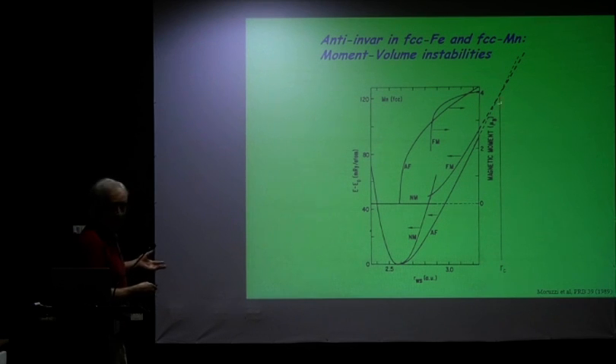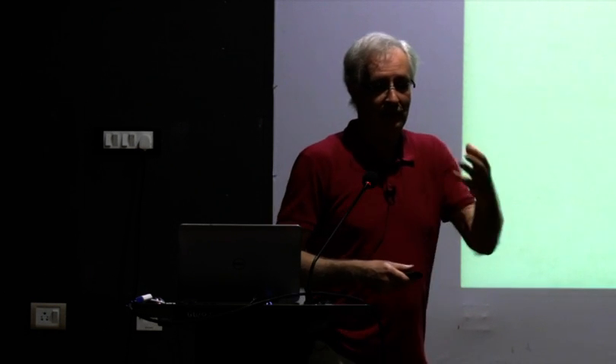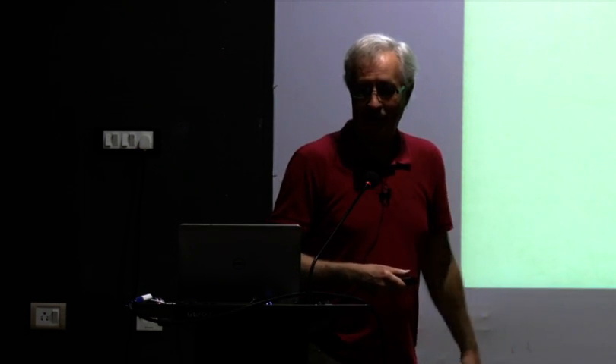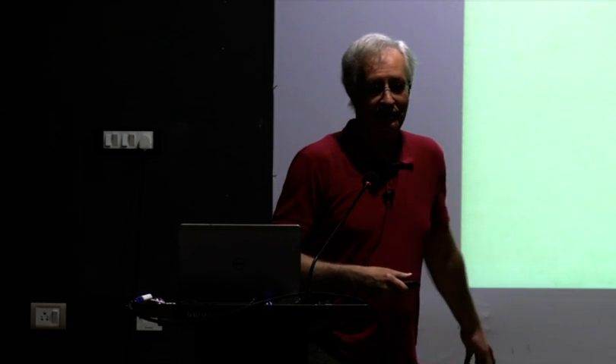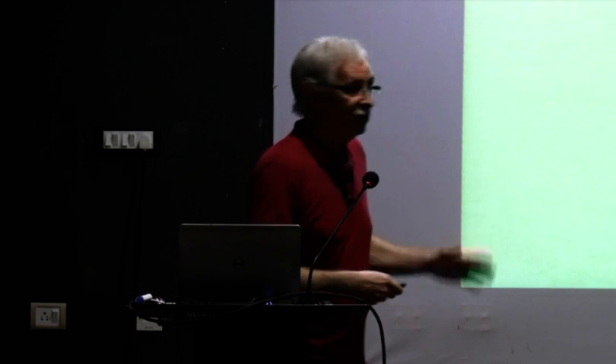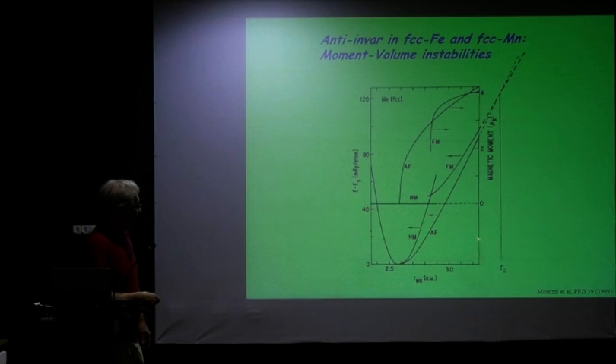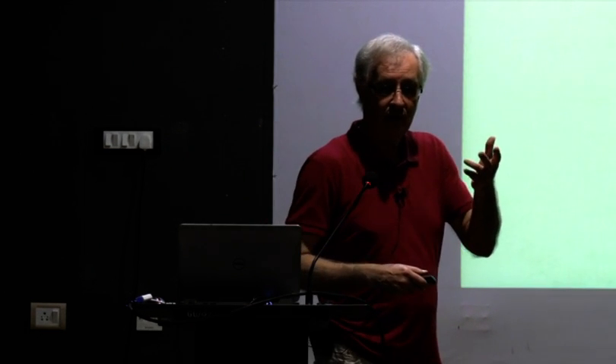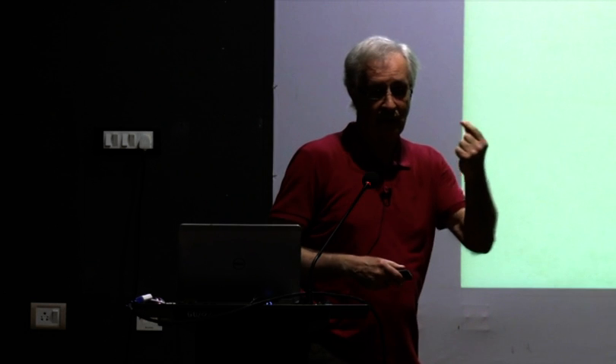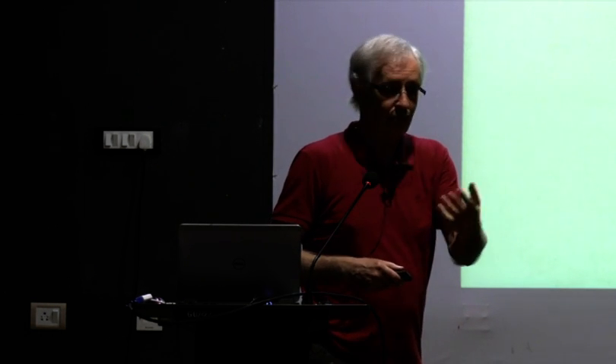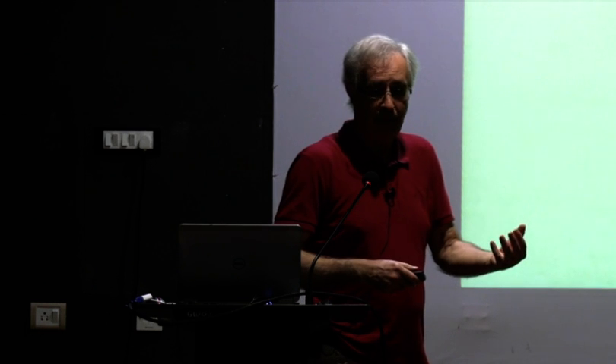well, if the meeting point were here, this is just too huge. So if you have antiferromagnetic manganese, just by heating it, you don't get ferromagnetic manganese. But if you make an alloy, a compound, with a composition that has a volume close to this radius here, then all you have to do is heat it and cross this. So in the case of Heuslers, you are very close to ferromagnetic transitions, like what we have in our shape memory alloys, yeah?